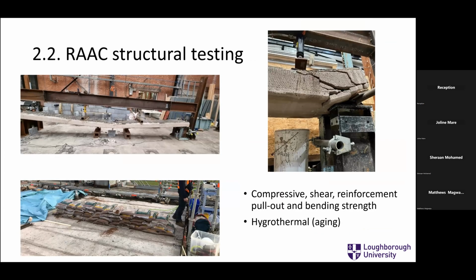Then we did some structural testing. Partly in the lab, we took about 20 planks out of hospitals and tested them full size in the lab. Compressive shear testing, pull-out testing, bending. We also did some on site. So you'll see a live test on site there. That is bags of sand. So those are bags of 25 kilograms sand stacked up on one plank until it failed.